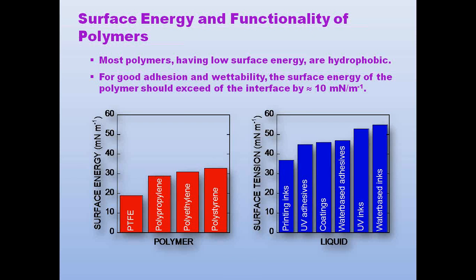If we focus specifically on polypropylene, for instance, which has a native surface tension of about 29 to 30 dynes per centimeter, or millinewtons per meter, and we look at the surface tension of solvent-based inks, which usually have a surface energy of about 36 to 37 dynes per centimeter, you can see that the existing surface energy level for polypropylene is inappropriate to at least create a base level of adhesion. And so it's necessary to raise that surface energy by approximately, again, that 10 millinewton per meter benchmark or incremental increase in order to achieve a satisfactory level of adhesion with solvent-based inks.